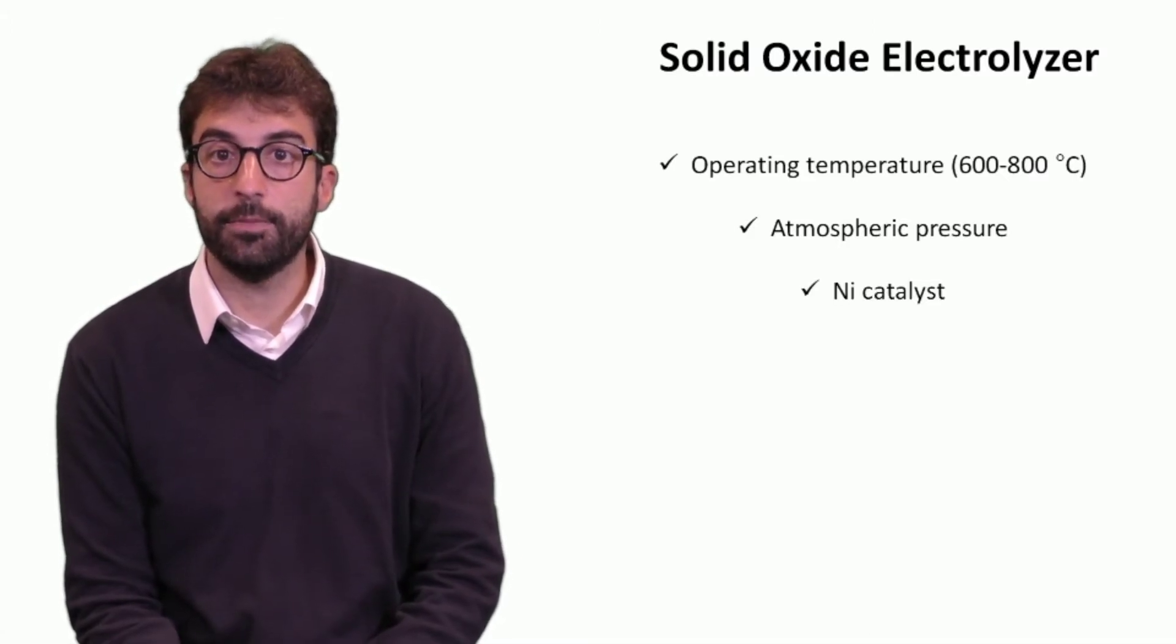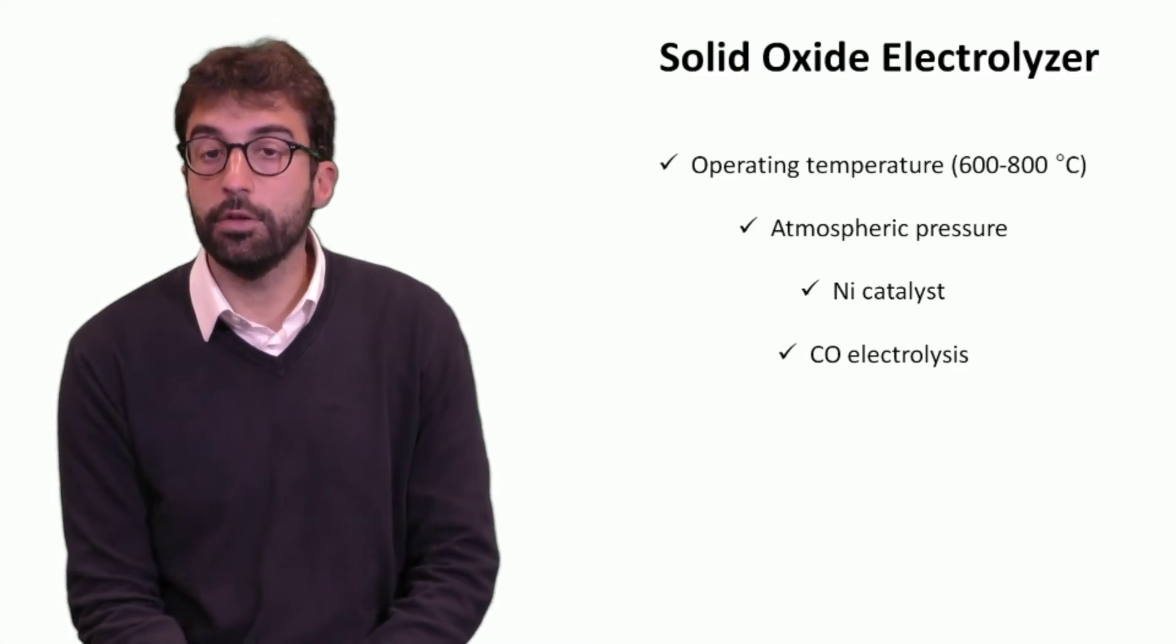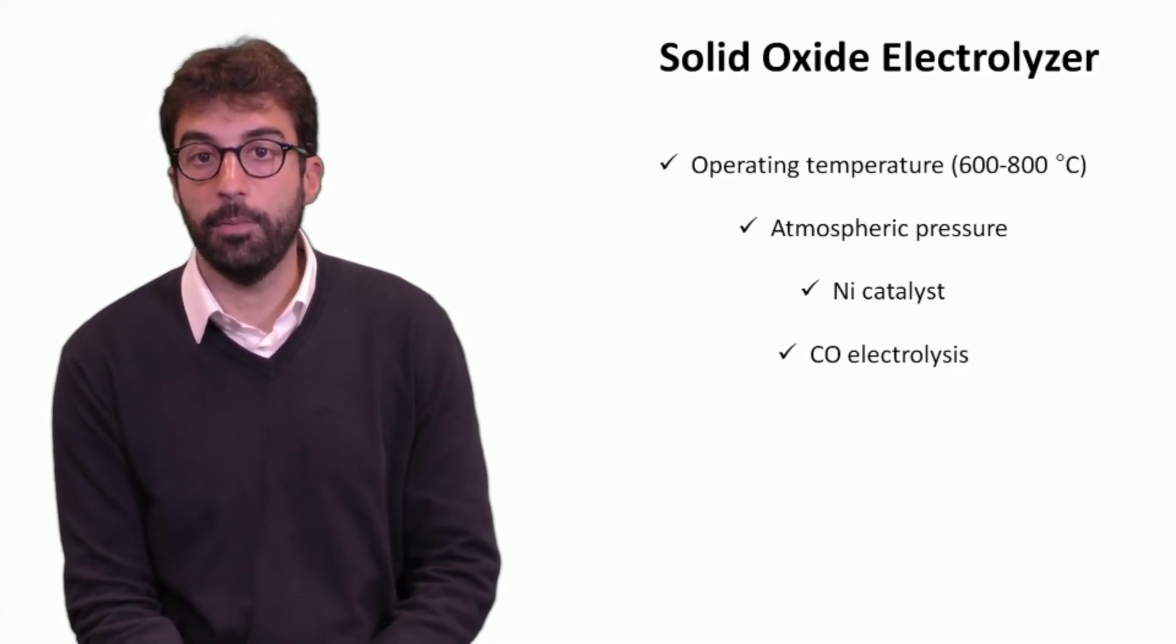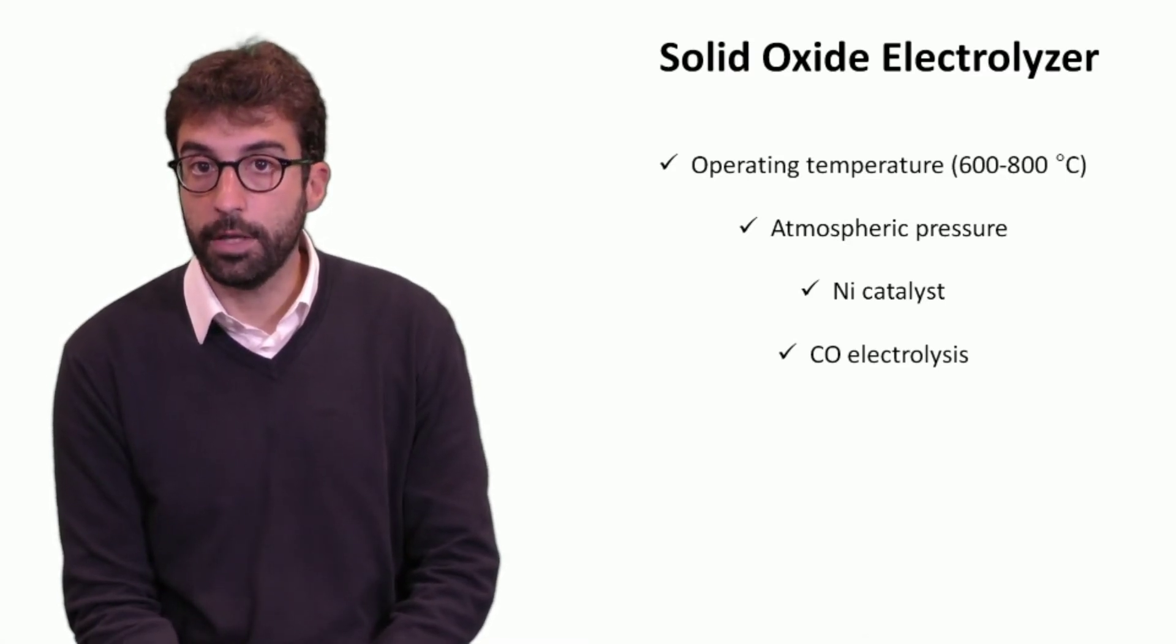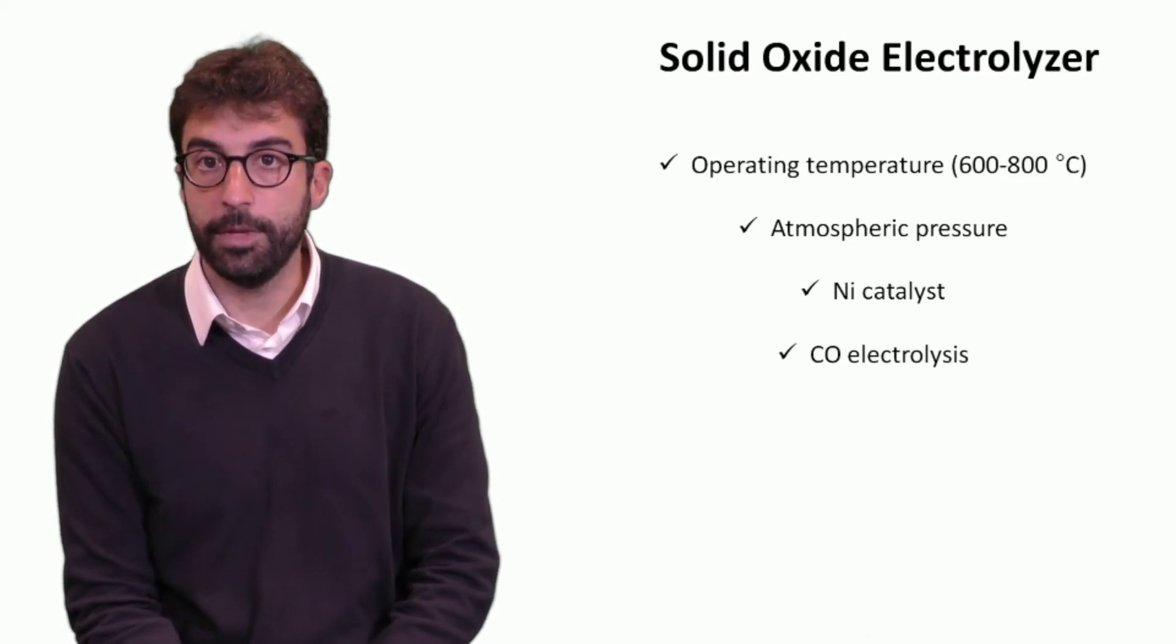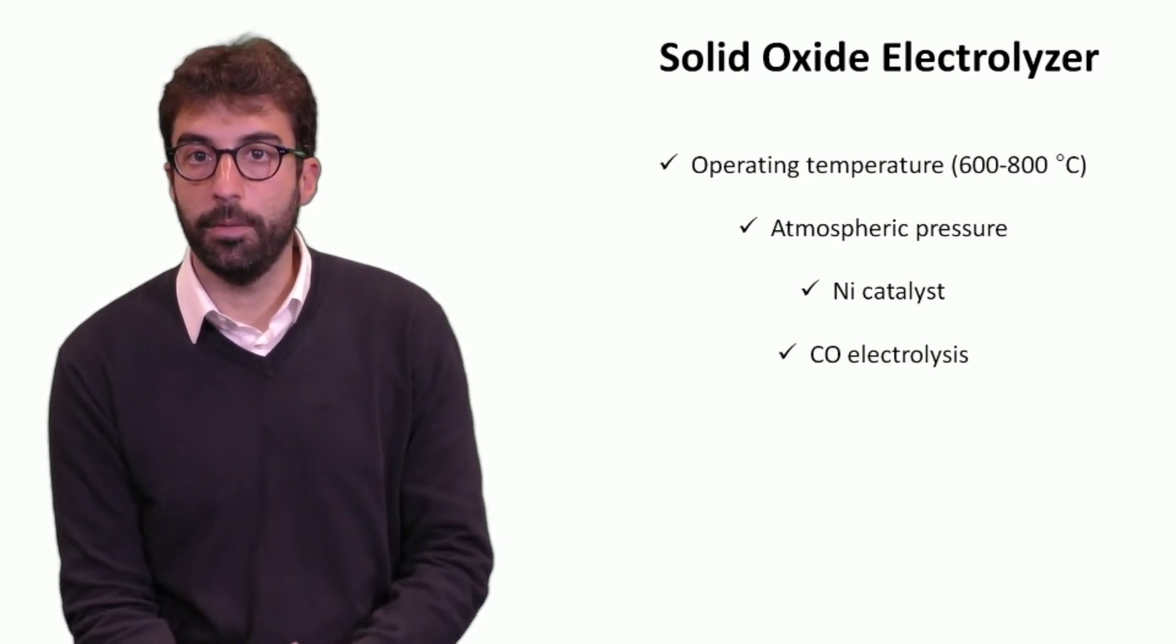Catalyst used is nickel. This is pretty important because it allows not only the electrolysis reactions but also other reactions that may take place inside. This usually happens when we have CO2 electrolysis, which is a potential development of these technologies, because nickel is a low cost and extremely stable catalyst when operating with carbonaceous fuels like carbon monoxide.